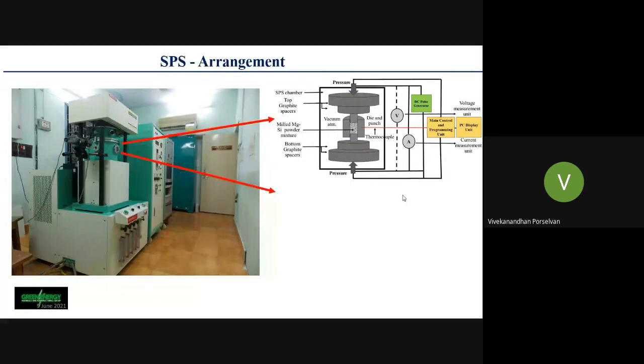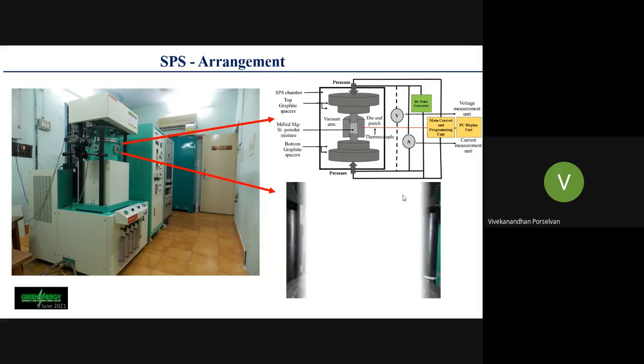With the conventional approaches, which have the limitation of 10 to 15 degrees Celsius per minute, where we want to do the sintering at about 1000 degrees Celsius, we need some 4 to 5 hours, including heating and cooling cycles. Whereas in SPS, due to the higher heating rate, namely 800 to 1000 degrees Celsius per minute, you can finish your sintering process in a few minutes. Thereby, you can very much overcome the traditional grain growth challenges.